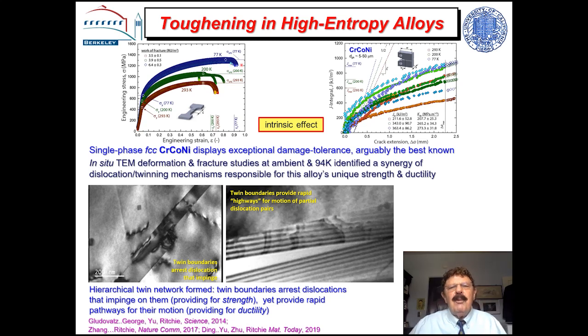When we go to low temperatures, liquid nitrogen temperatures in blue, you can see that they get stronger at lower temperatures. Well, that's predictable, but they also get more ductile, which is highly unpredictable. In fact, the properties of this material at liquid nitrogen temperatures have 90% tensile ductility at 1.3 gigapascal strength, which is remarkable. We do a toughness test on these.